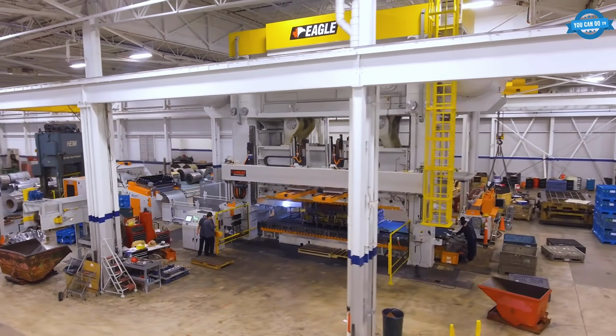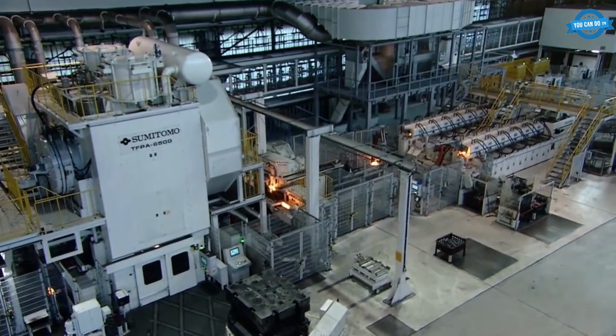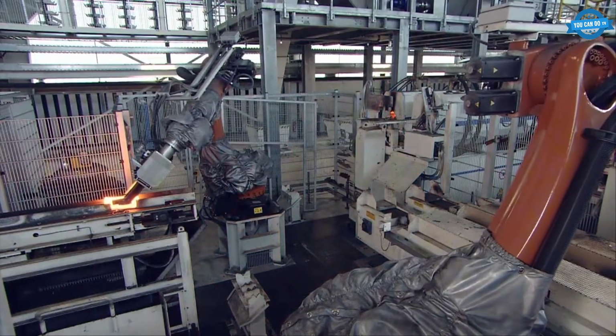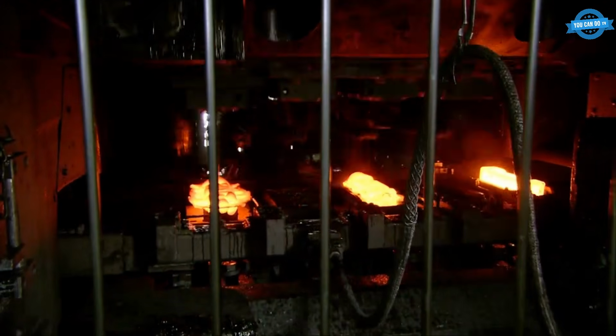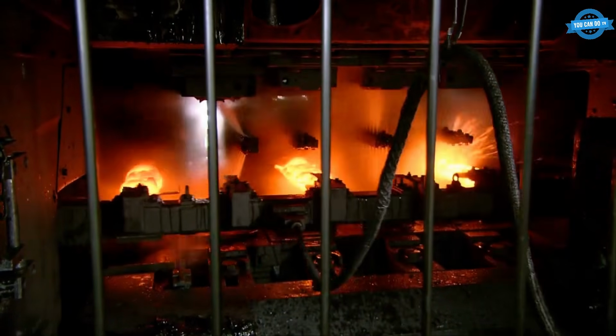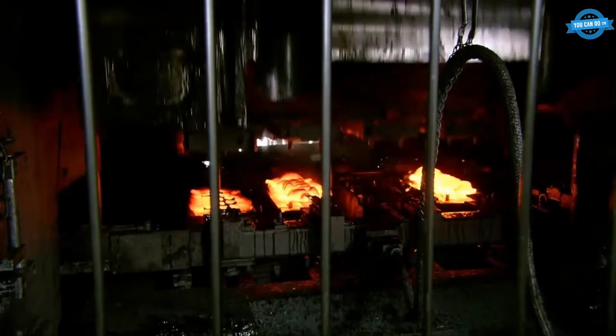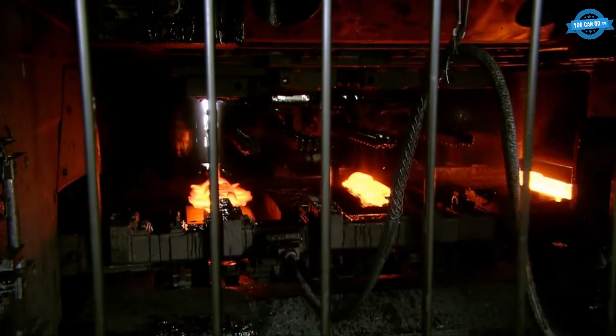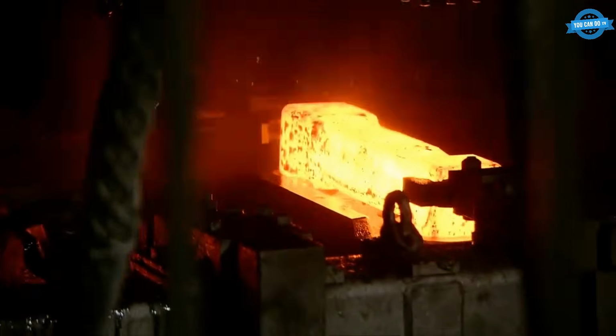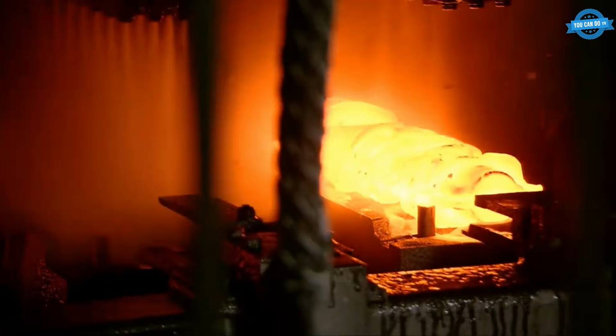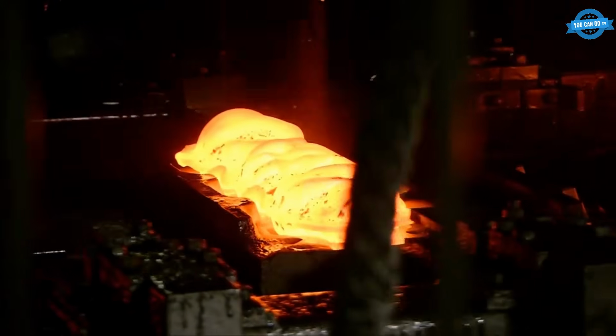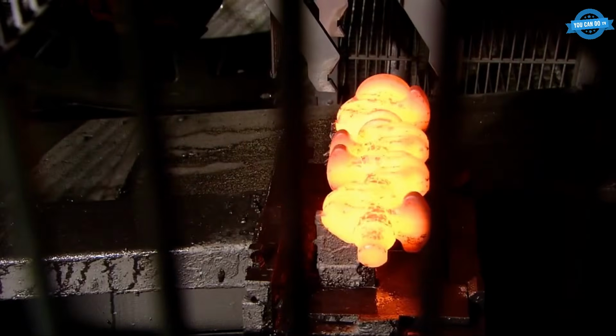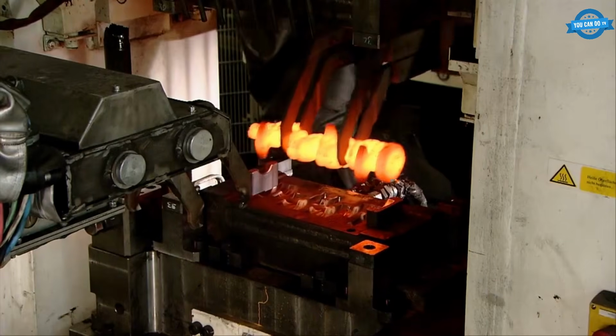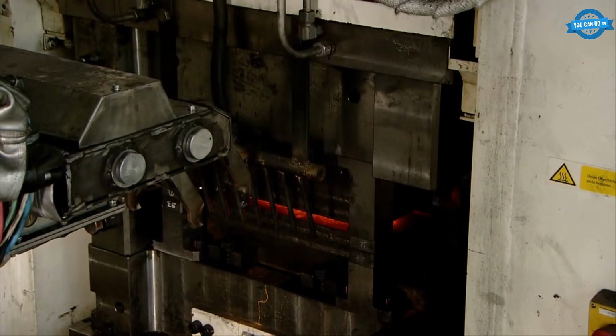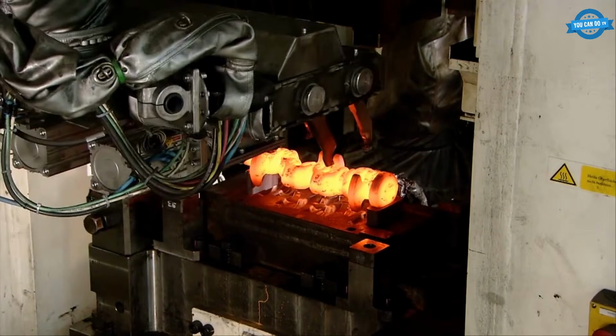Now more than double the force and heat the metal until it glows orange, and you're at a completely different level of manufacturing. A 6,500-ton hot forging press for automotive crankshafts. A steel billet gets heated to somewhere around 1,200 degrees Celsius until it's soft enough to move under load, but still fully solid. Then a die closes on it with enough force to redistribute the internal grain structure, not just squash the outside. That grain structure is why forged crankshafts survive inside your engine at 6,000 revolutions per minute for a decade. The metal fibers actually flow along the shape of the part instead of getting cut across the grain like a machined one would.